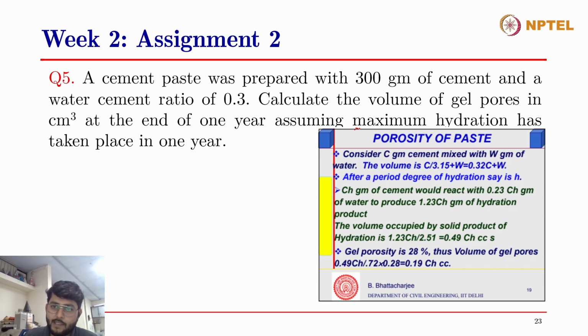Moving on to the fifth question: a cement paste was prepared with 300 grams of cement and a water to cement ratio of 0.3. Calculate the volume of gel pores in cm³ at the end of 1 year, again assuming maximum hydration has taken place in 1 year. So again, the phrase to focus on here is that maximum hydration has already taken place.